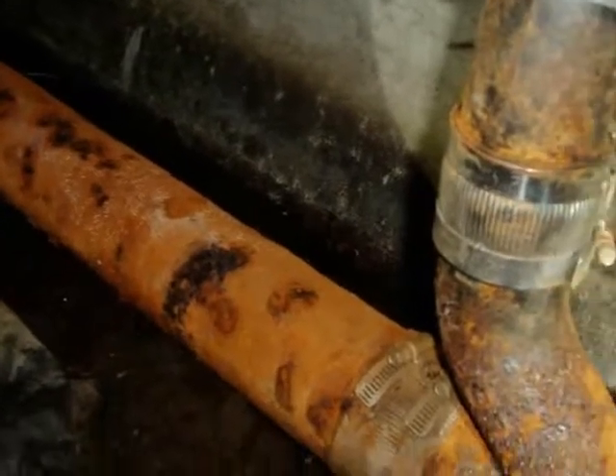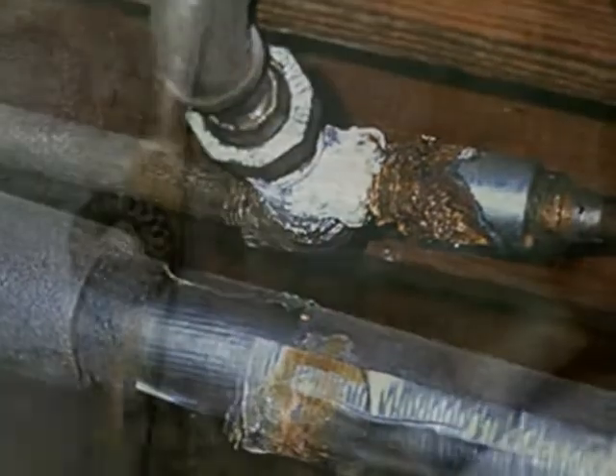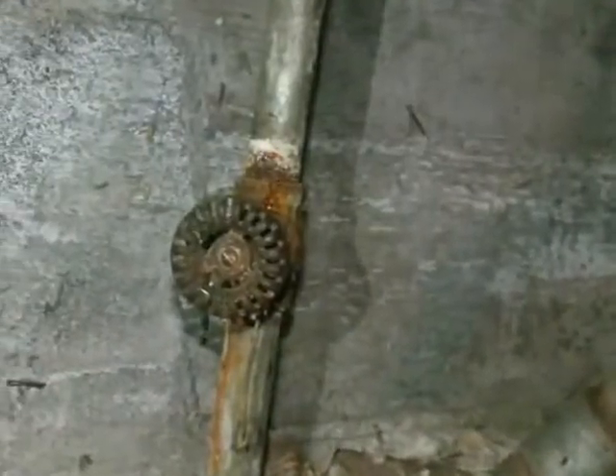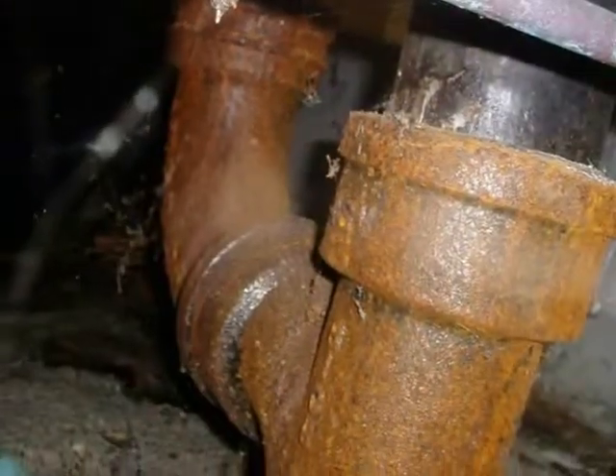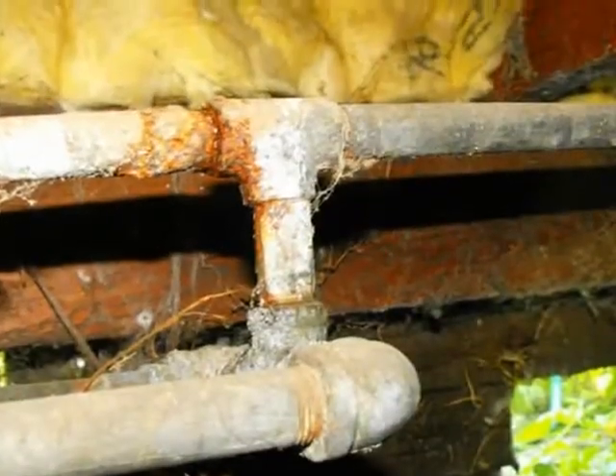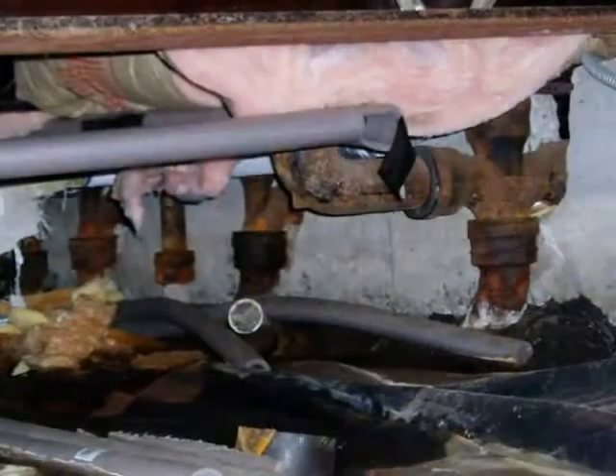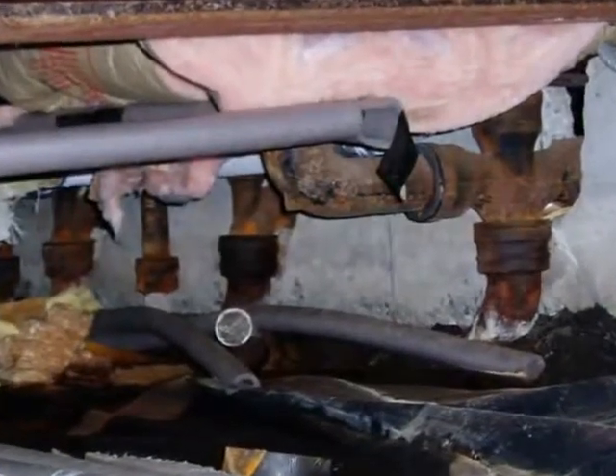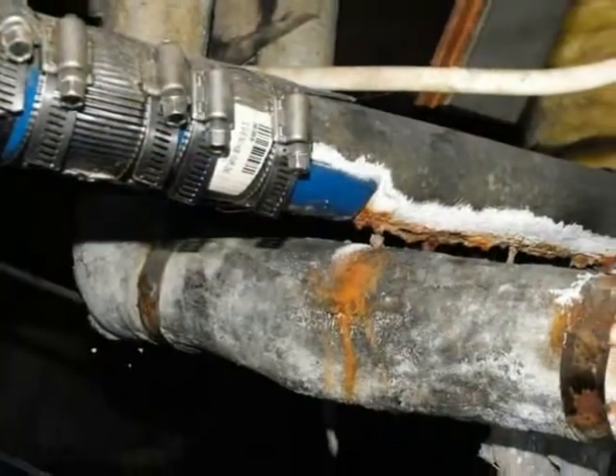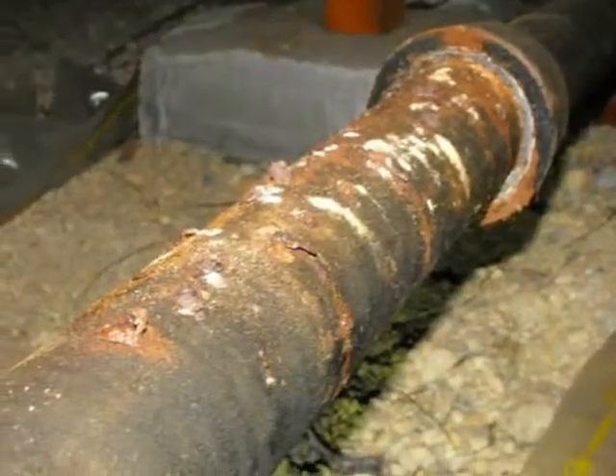At older homes, the inspector often finds aged metal plumbing pipes. Problematic piping materials include galvanized steel, cast iron, and lead. The useful life of steel or cast iron pipe is 40 to 60 years. Since these materials were phased out during the 1960s or before, it's reasonable to assume that any old pipes are deteriorating and will have to be replaced in the not-too-distant future.